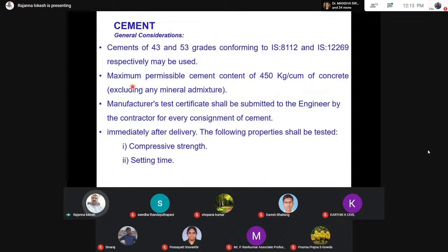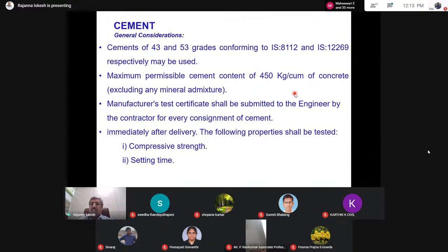In all possibility, the maximum cement can be 450 kgs per cubic meter, whereas for PQC, the minimum cement content is specified at 400 kg per cubic meter. So it is important for us to get the manufacturer certificate before start of the work. Once the cement is procured in the site, it is important for us to check the compressive strength as well as setting time.